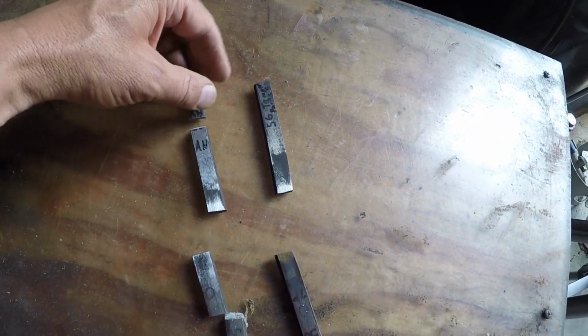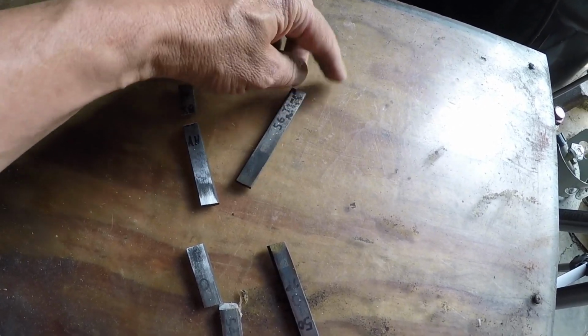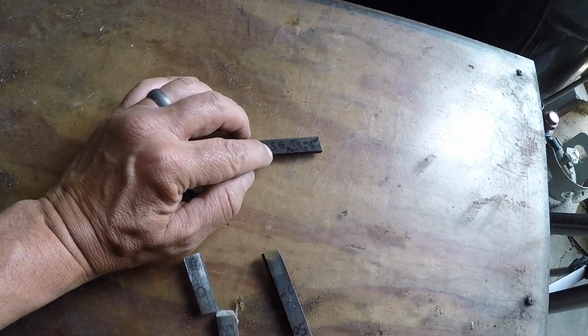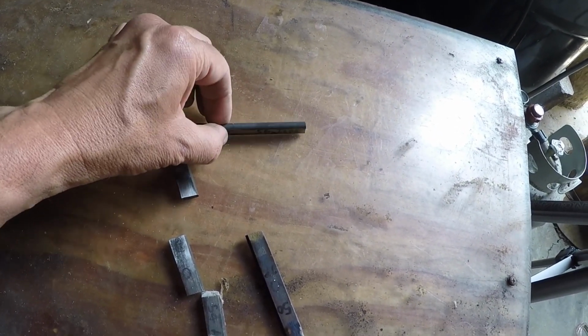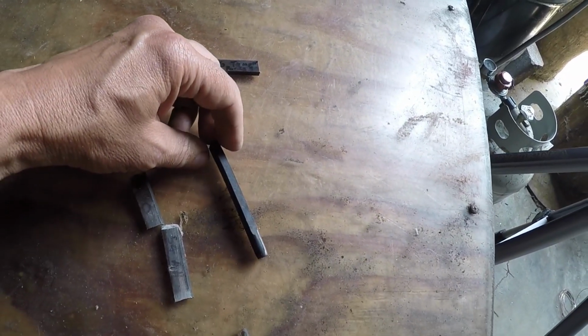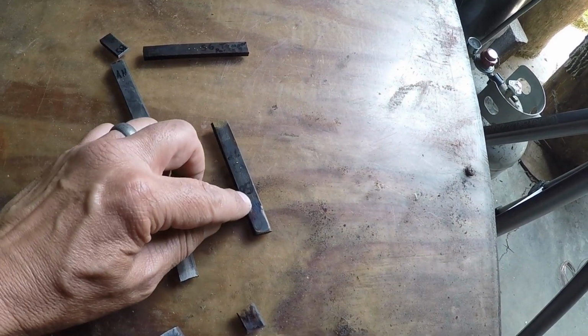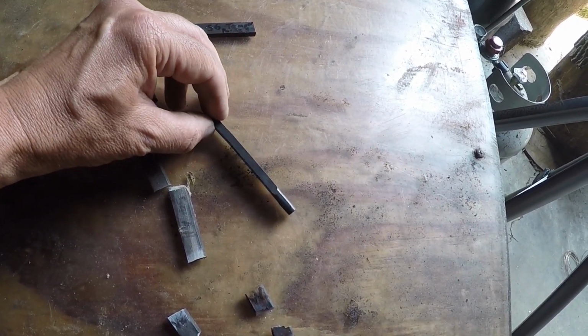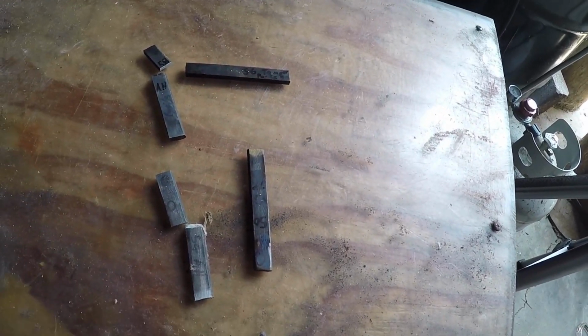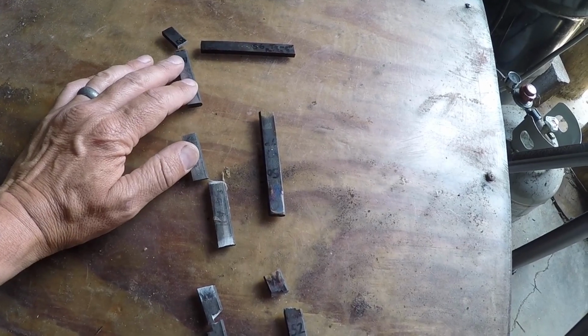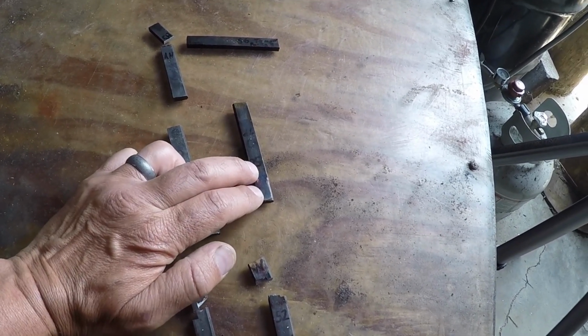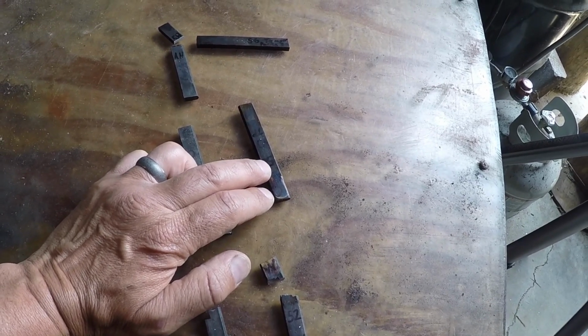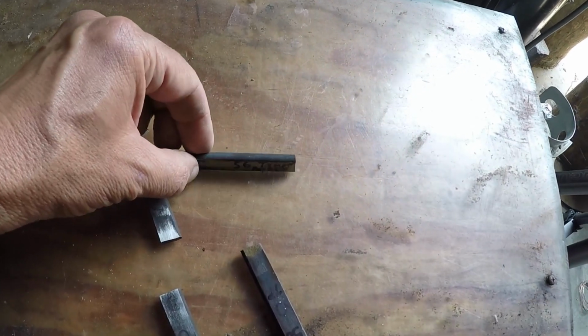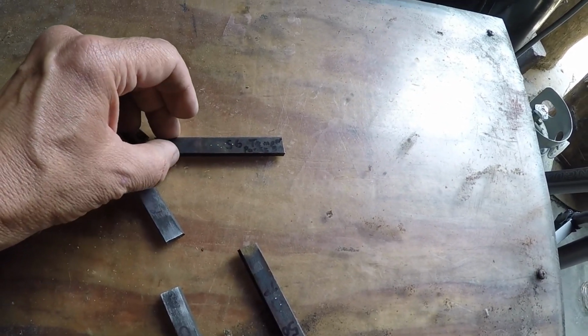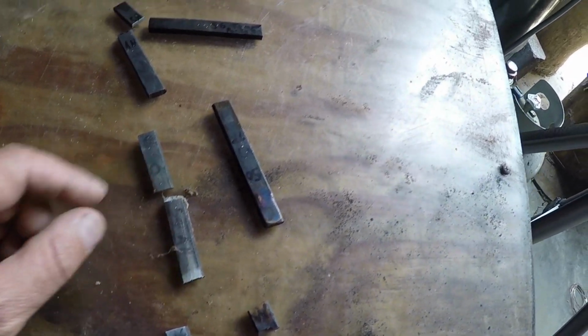So the success story was the Parks 50 had a higher hardening range of 56 that succeeded in not breaking and actually less deformation. The oil that was our canola succeeded with a 50 Rockwell, and it bent a little bit more than the Parks did. But one, oil was a better quench. Two, at that kind of Rockwell hardness, you're not going to have as easily a chance of breaking. But because of the preferred quenching style, I believe our 56 Rockwell, which this one was 52, this one was 54, those were both less than the 56 and both shattered.